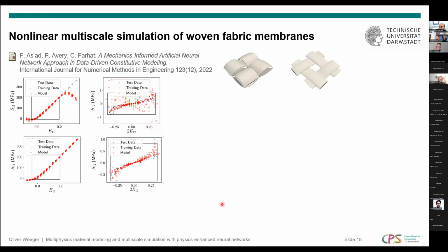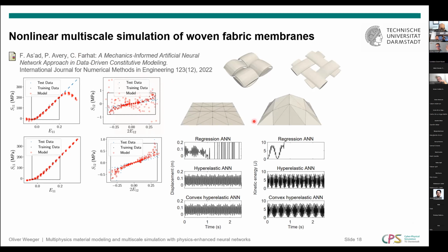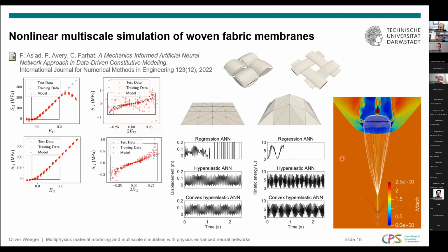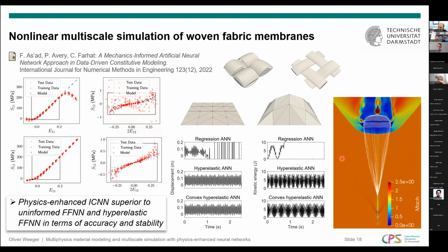And we were not the only ones who worked on this topic. So basically in Ellen Kuhl's group at Stanford, they developed a very similar model, and they did a very good job in implementing it into a finite element simulation and showing interesting results where they show the dynamic vibration behavior of such a membrane, where the hyperelastic neural network and the convex hyperelastic neural network are much more accurate and much more stable than a simple regression neural network. And then they also showed that these kinds of material models can be used very well also in fluid-structure interaction simulations, for instance. So the physics-enhanced input-convex neural network gives a superior accuracy to completely uninformed neural networks in terms of accuracy and stability.